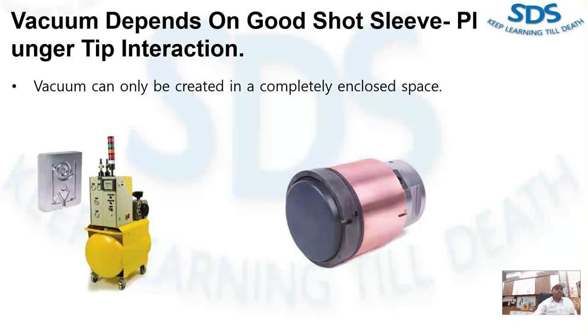Before the injection shot occurs, a vacuum is drawn in both the shot sleeve and the mold cavity. The vacuum is maintained until the injection cycle is completed. Almost all of the air is positively evacuated from the mold. A good vacuum in a mold cavity enables the alloy to flow into blind recesses in the complex shape.